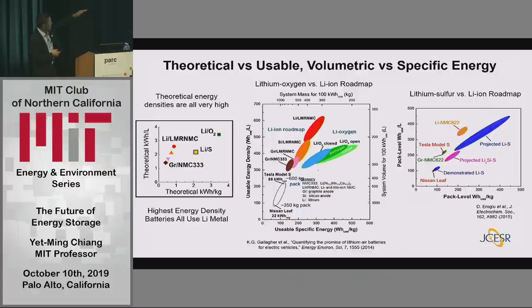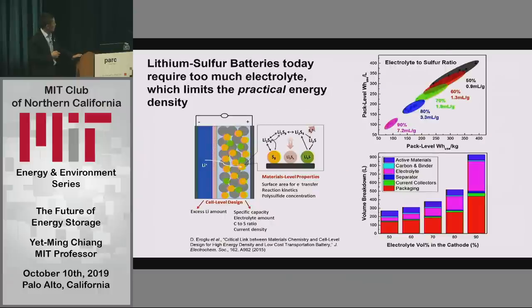The other thing I want to point out here is that at the top of both charts involves lithium metal. And the lithium ion battery is famous because it does not use lithium metal. It uses graphite that stores the lithium ions, but it does not actually have the metal in it intentionally. If you produce a lot of the metal, then you actually are causing trouble. So the reason these roadmaps end with lithium metal is because today, across the field, our focus is once again trying to make lithium metal successful. And I'll tell you why it hasn't been so far.